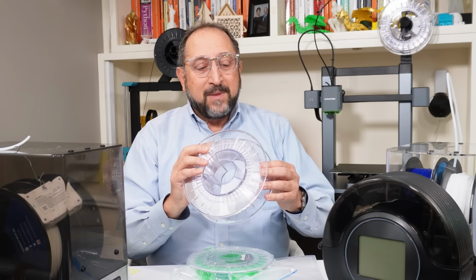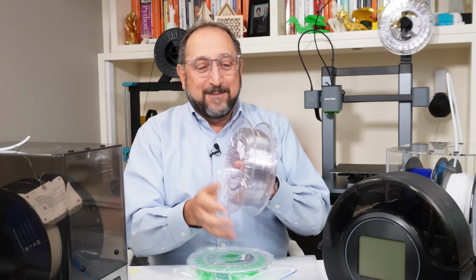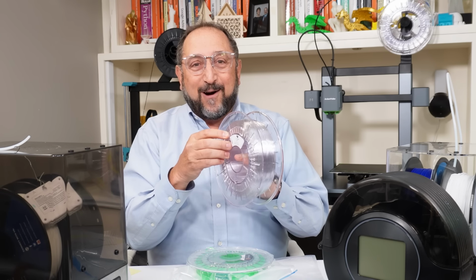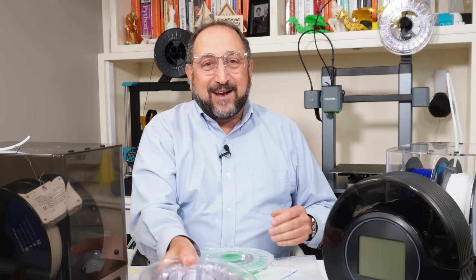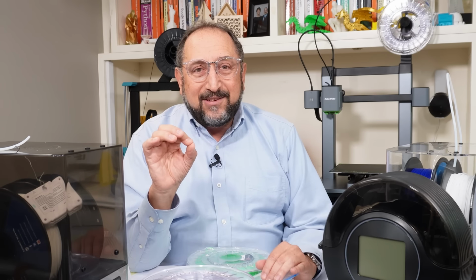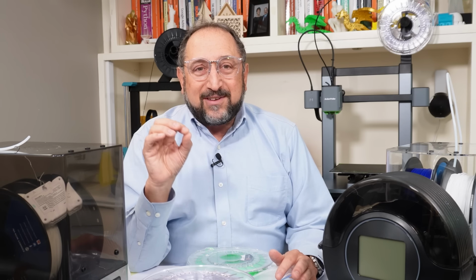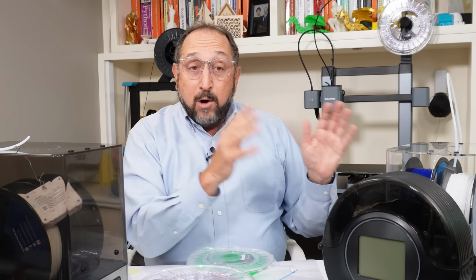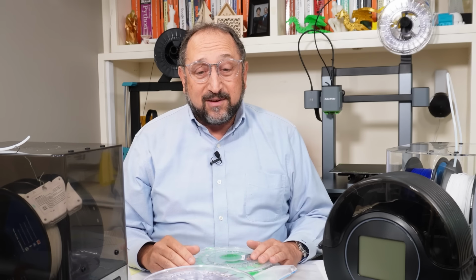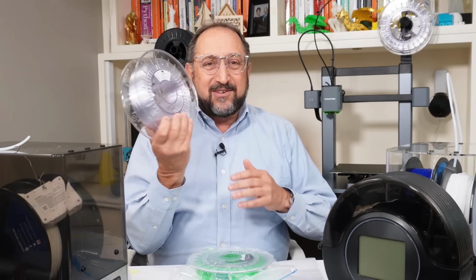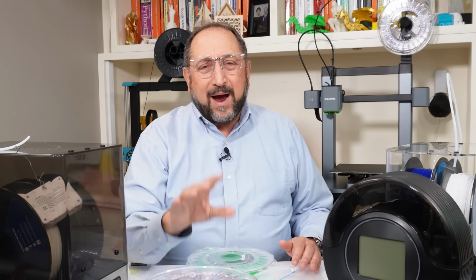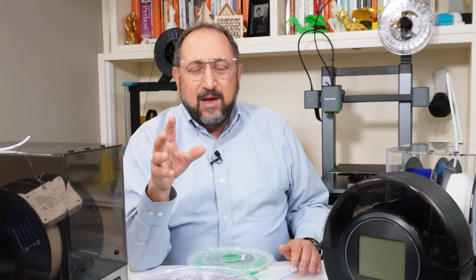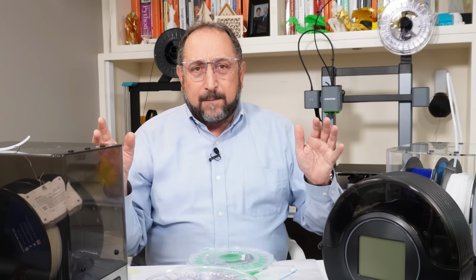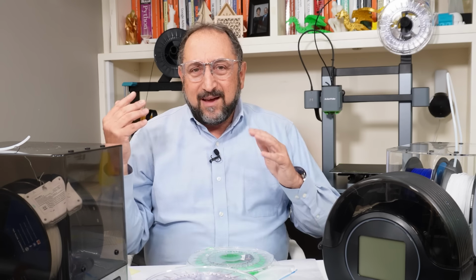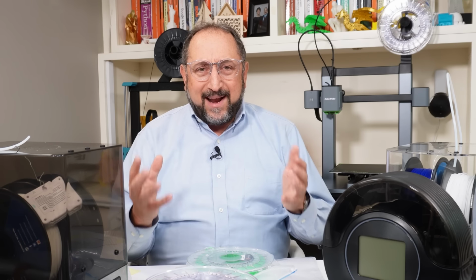And I came back, and I had a block of XT filament. This is no longer usable. You can't get it off the reel. Some of it's loose, some of it's all stuck together. So the first rule is dry your filament at the lowest temperature possible. So most of the print dryers start at 50 degrees Celsius. It ends up that PETG, which this is a variant of, should probably never be dried at above about 55 degrees Celsius. The only filaments you really dry at a much higher temperature are nylon, but they also print at a much higher temperature.